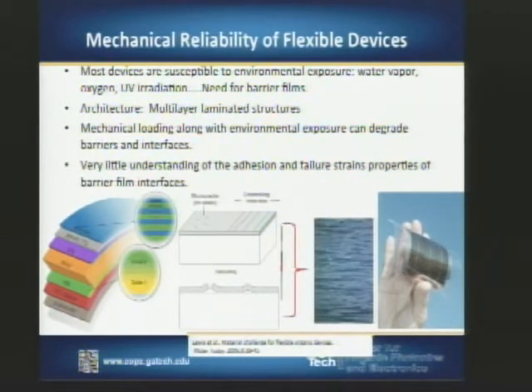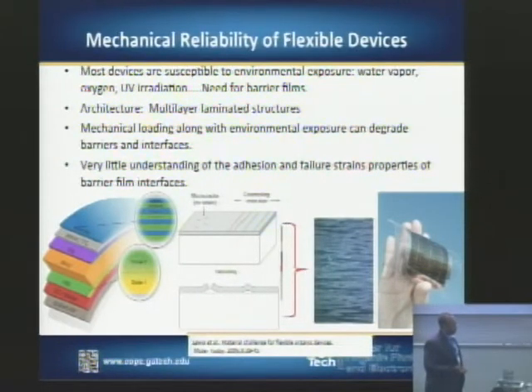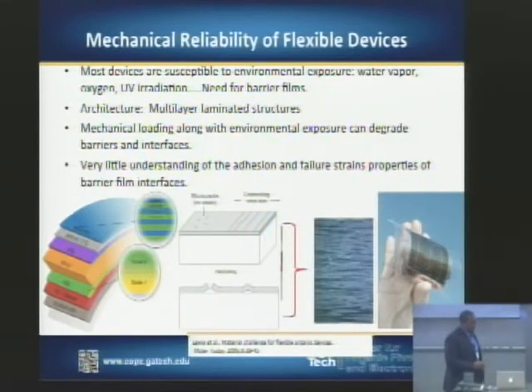Another aspect of the survivability or reliability of devices, when we start talking about flexible organic photovoltaics, OLEDs, or other types of electronics, is that we want to understand how some of these critical barrier films, or critical oxides we deposit by ALD, hold up in flexural applications. The main concern a lot of us have is the cracking of these oxide layers. So we'd like to understand what the strain to failure is, and what aspects of the processing lead to different levels of strain to failure.